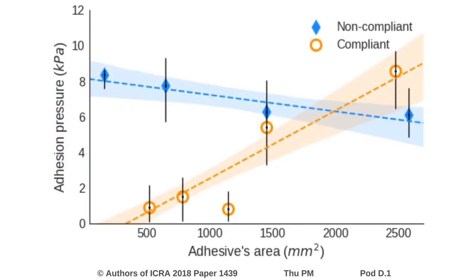On small area pads, this results in reduced adhesion strength in compliant designs as compared to non-compliant designs. On large area adhesives, the benefit of higher overall contact area due to high bending compliance negates the effect of high stored elastic energy, thus resulting in improved performance of compliant adhesives as compared to non-compliant adhesives. Our work demonstrates that the adhesive's design strategy and material choice may depend on the size of the intended device.